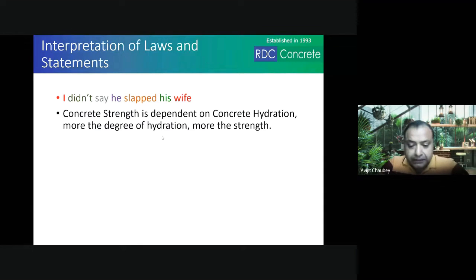So what I try to mean is, each cement particle must hydrate. There should be no cement particle whose surface is not hydrating. Every cement particle's surface must hydrate, for which you require a good quality admixture so that all the cement particles are away from each other, not bonded with each other, so that the surface does not fail to get exposed to water for hydration. If that is the case, these lumps of cement will give you lower strength. So the cement particles should disperse. All the cement particles must come in contact with water, and all the cement particles must hydrate.